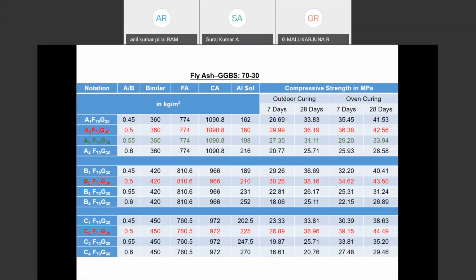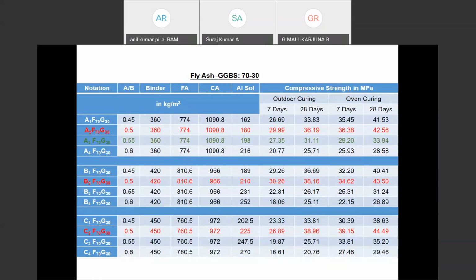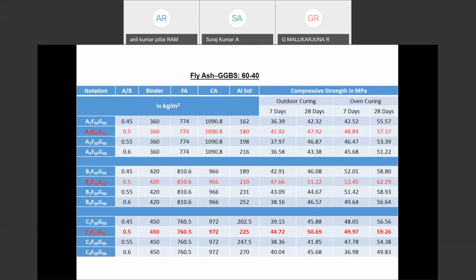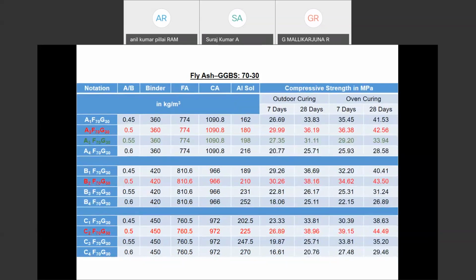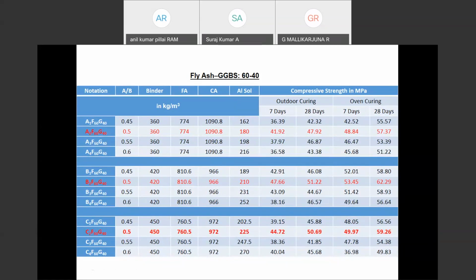And next, these are the different combinations of fly ash and GGBS we considered, for 70-30 and 360 kg per meter cube, 420 and 450 kg per meter cube. Based on trials, we went for both outdoor curing and oven curing conditions for 7 and 28 days. Here for 7 days, we get the maximum strength at 0.5. For all the mixes of 420 and 450, we observed the maximum strength at an alkaline to binder ratio of 0.5, for both oven curing and outdoor curing. And this is for the mixes of 60% fly ash and 40% GGBS. Whenever we increase the GGBS content, automatically strength improvement was observed here.